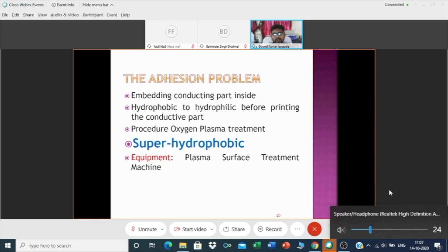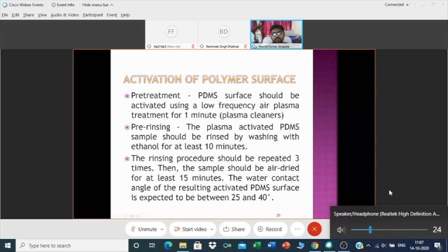So this plasma treatment: first you have to pre-treat the PDMS surface. You have to expose it to air plasma treatment. That means suppose you have a glass desiccator, the desiccator I showed you previously. You have a glass one, and you suck the air out of it, and you fill it with air, oxygen, and you put it into the plasma treatment machine, plasma cleaner, and you expose it for 1 minute, or you can go for shorter durations also, it will work. And after activating, you just rinse it with ethanol for 10 minutes, and then you repeat this process 3 to 4 times, then air dry it.